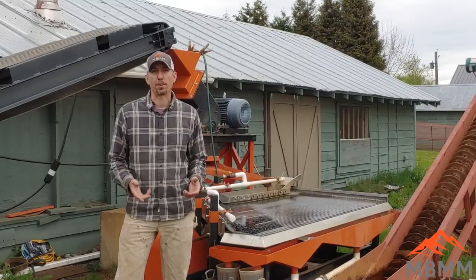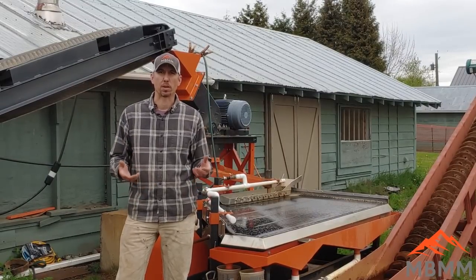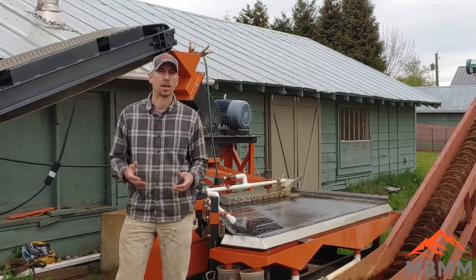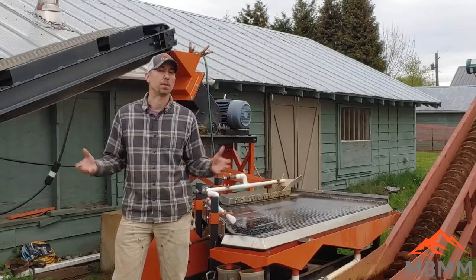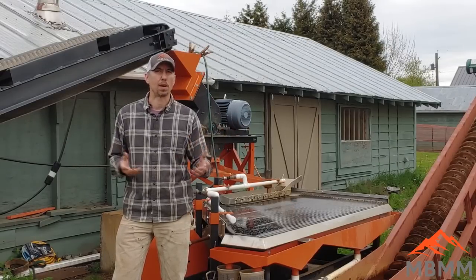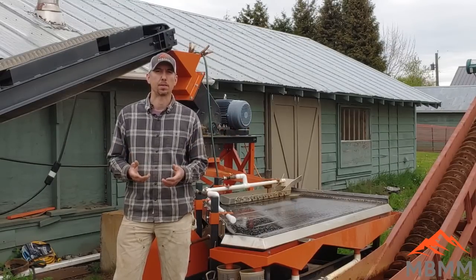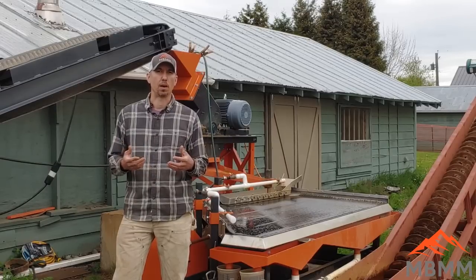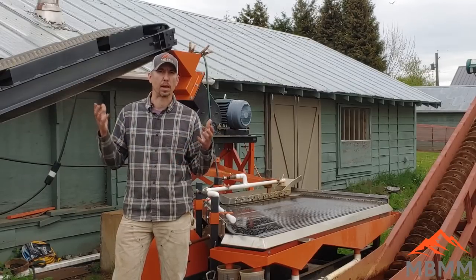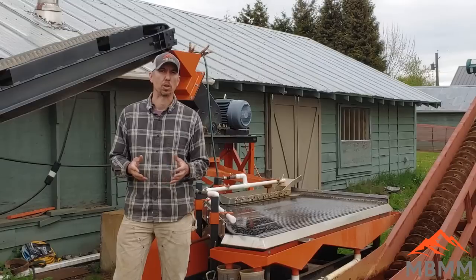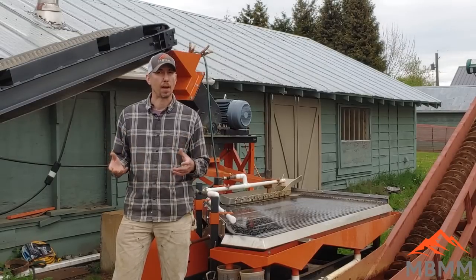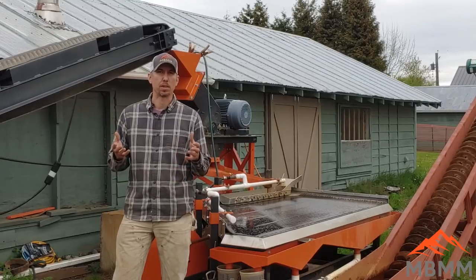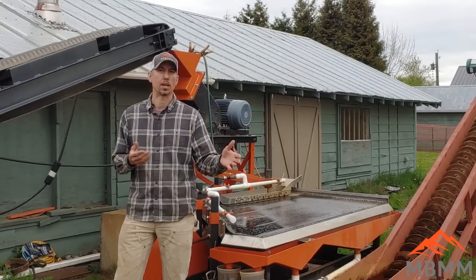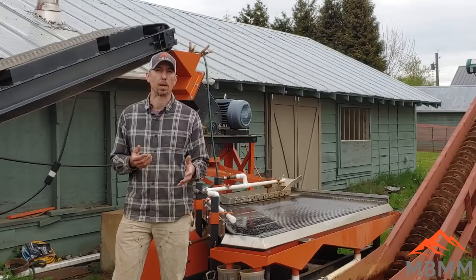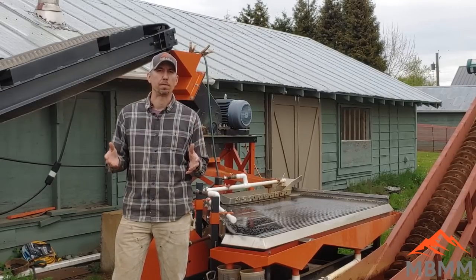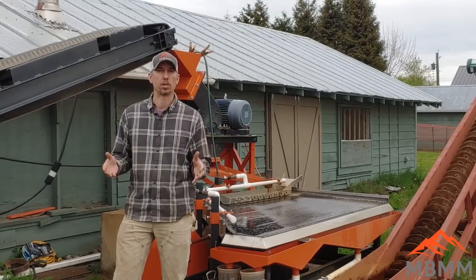So we covered a lot of ground, and we looked at all the details on our recovery and our grind size and all that stuff. Now I wanted to pull back and look at some of the bigger picture and do kind of a rough back-of-the-napkin analysis of what we could expect if we implemented the system up near the dump pile on this claim. So we're recovering about 75%, plus or minus, and with 20 grams a ton in the ore, that means we're recovering about 15 grams a ton.